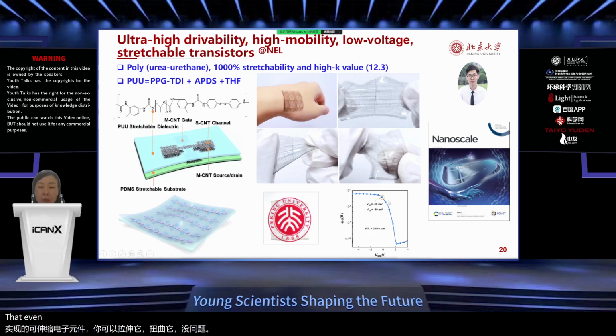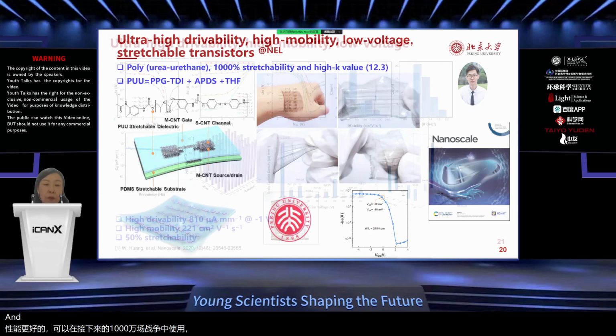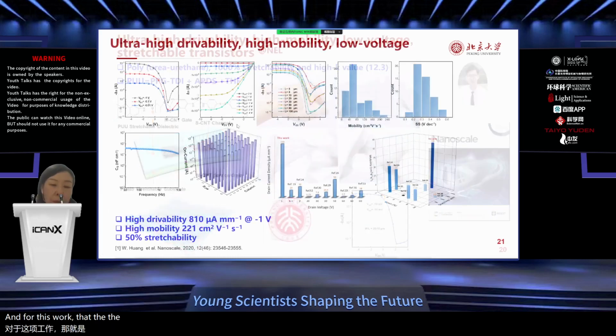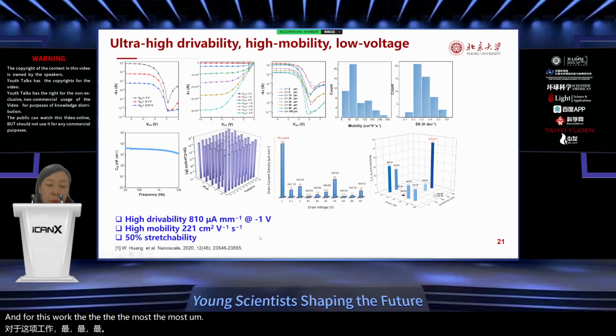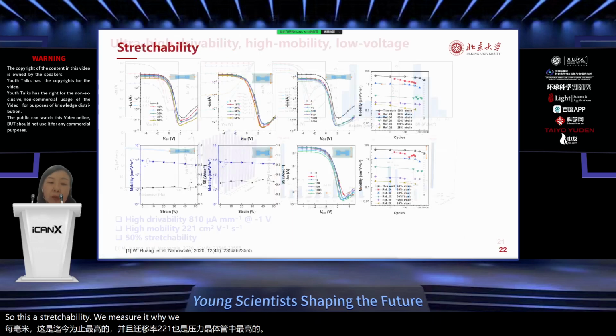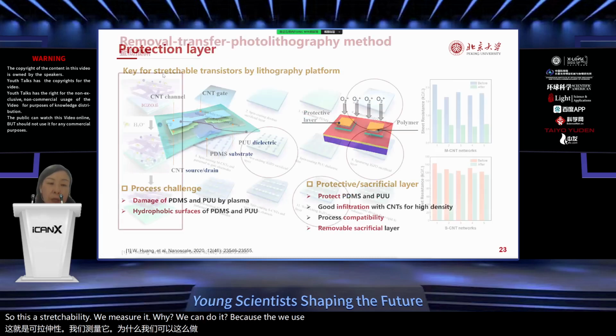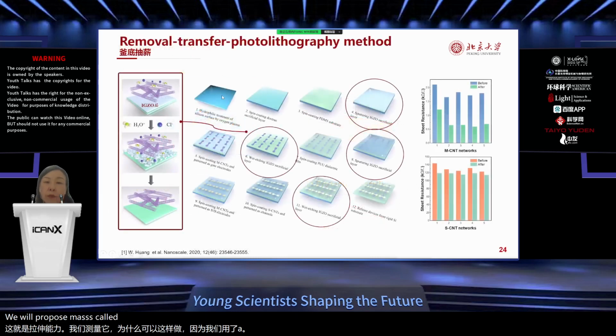The even better performance is that it can work at a negative 1 volt VDD. And for this work, the most important point is the drivability reaches 810 μA per millimeter. This one is the highest until now, and the mobility of 221 is also the highest for a stretchable transistor. This is the stretchability. We measured it. Why can we do it? Because we propose a method called the remove-transfer photolithography method.